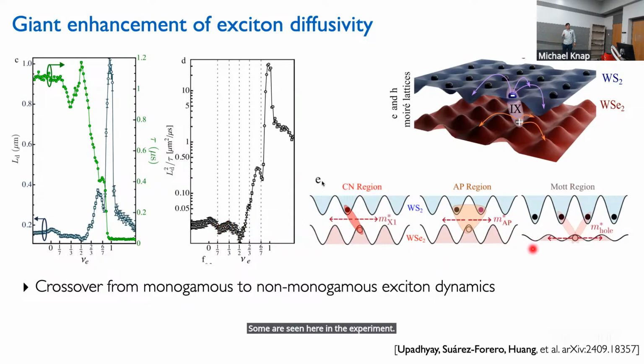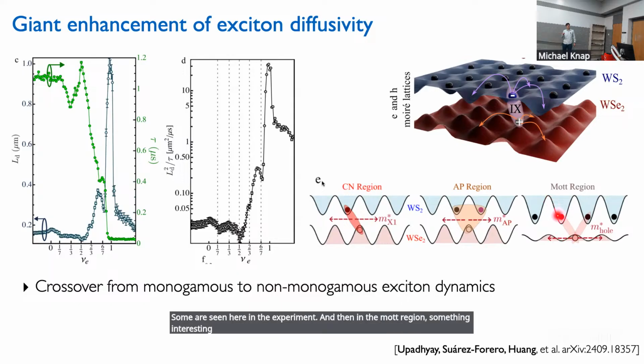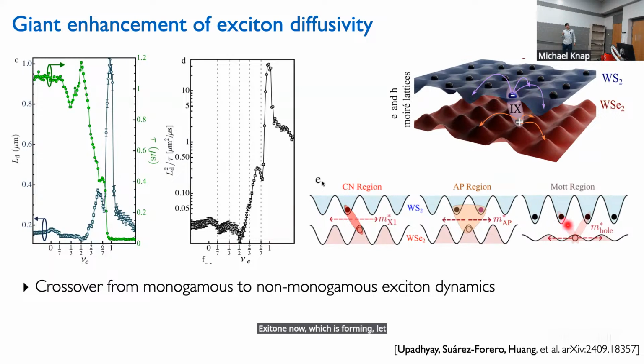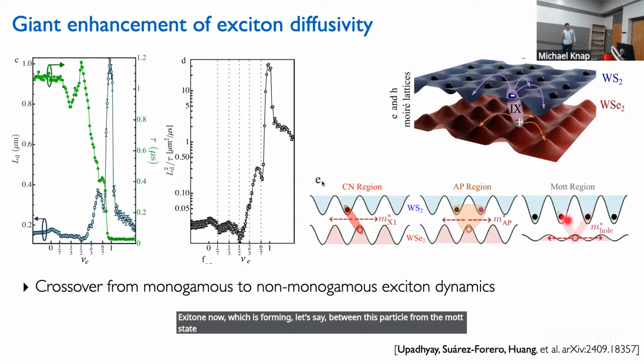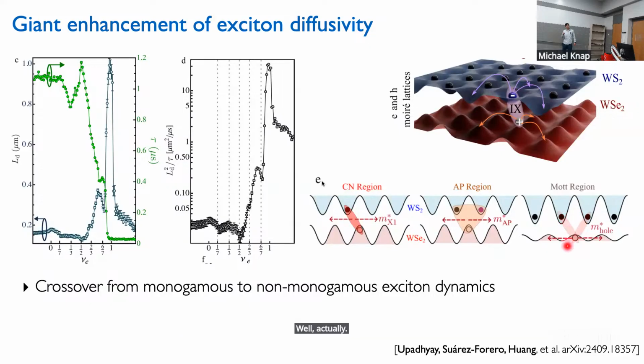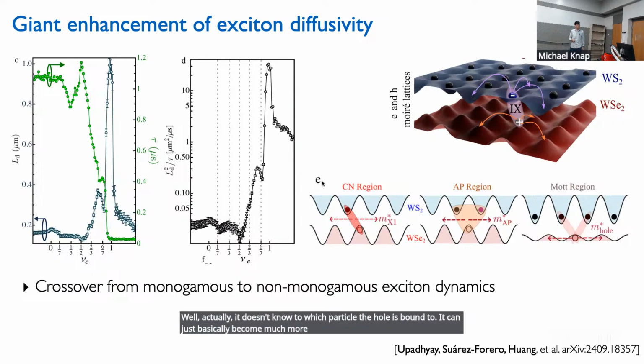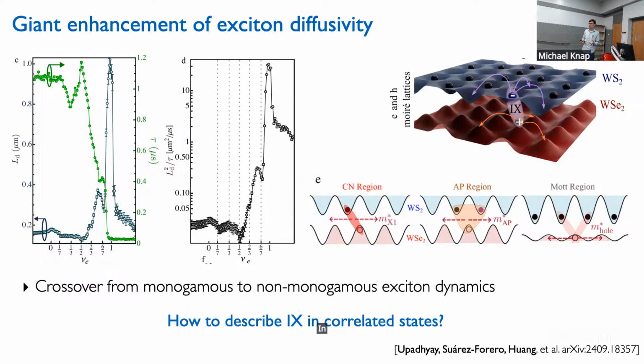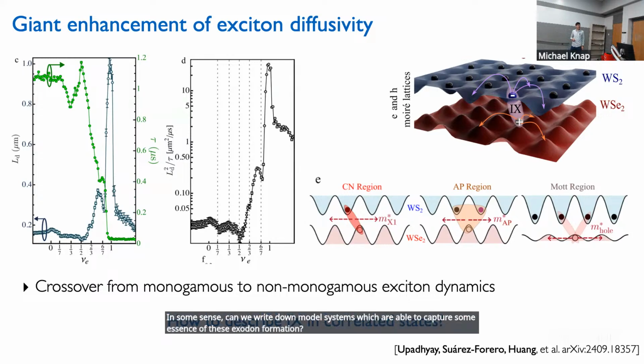And then in the Mott region, something interesting is happening, because there, the exciton, which is forming between this particle from the Mott state and the hole here, actually doesn't know to which particle the hole is bound. It can basically become much more mobile by going through the system. We called it a crossover from a monogamous exciton dynamics to a non-monogamous one where the charge carriers are shared. So the question is, can we make this a bit more quantitative? Can we write down model systems which are able to capture some essence of this exciton formation? That's what we set out with.